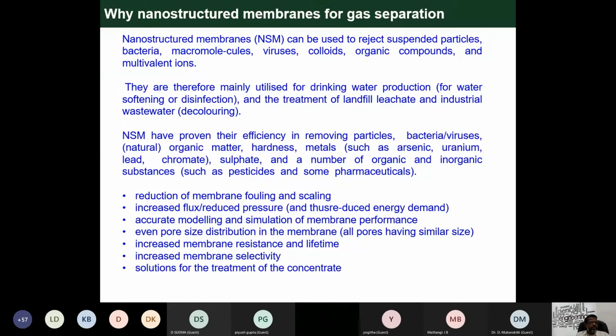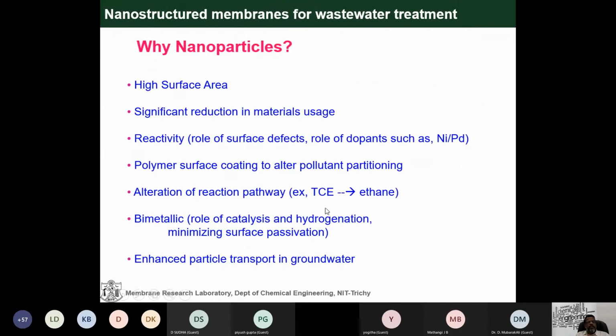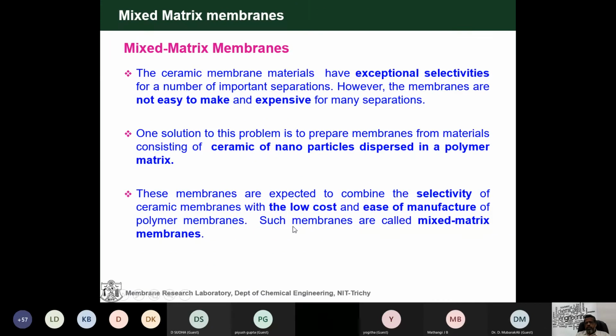Accurate modeling and simulation, even the pore size distributed through the membranes, whether smaller size or bigger size, is uniformly distributed, and increases the membrane resistance and lifetime, selectivity, and treatment of concentrate. That's the reason most of the nanomaterials are used. So it is called a mixed matrix membrane. The mixed matrix membrane is nothing but any kind of ceramic, that is inorganic materials, incorporated into the polymers. So we make the new materials.